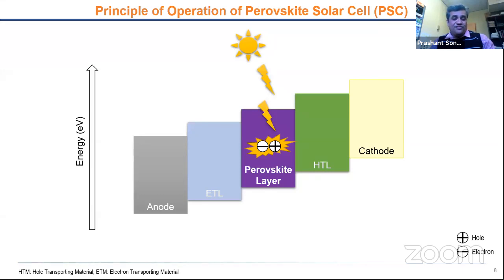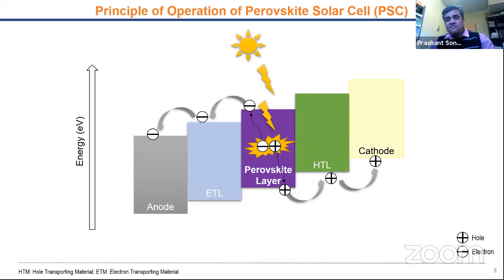And that is why the efficiencies of perovskites are quite high. And if you make thick devices, device efficiency is still quite good. That is not the case in organic solar cells. So once a photon bombards a perovskite layer, it forms an exciton, a hole and electron pair. This exciton then gets separated via the hole transporting layer, where holes go, and the electron transporting layer, where electrons go, and with respect to cathode and anode, we get the free charges, and those charges can be collected as a current. This is a simple principle.